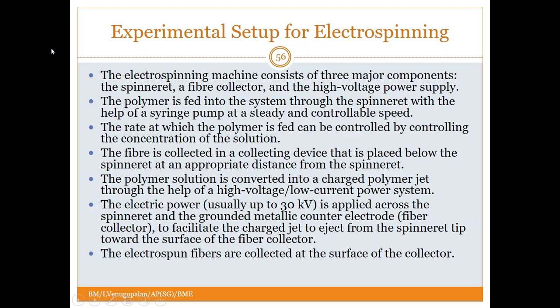So you have an experimental setup for electrospinning where you have a machine that consists of majorly three parts: the spinneret, a fiber collector, and the high voltage power supply. The polymer is fed into the system through the spinneret, and this is done through a syringe pump at a steady and controllable speed. You just use an infusion pump which steadily pumps the polymer solution into the spinneret. Now, the rate at which the polymer is fed can be controlled by controlling the concentration of the solution. The thicker the solution is, the rate of pumping would reduce, and if the solution is much thinner, then it can be pumped